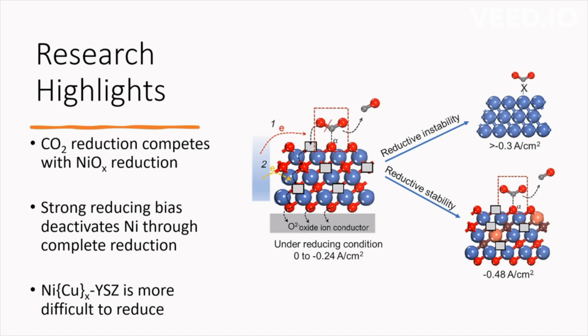While when we go beyond this current density, in case of nickel, it is completely reduced to metallic. Now there is no sufficient surface oxygen to carry out the CO2 electrolysis. While in case of copper, it keeps the structure intact as its oxide is more strongly bound, as the bond strength of the nickel-oxygen-nickel bond is more on copper doping, which helps to carry out the CO2 electrolysis even under strong reducing bias. So this type of mechanistic studies we are carrying out by using Operando studies.